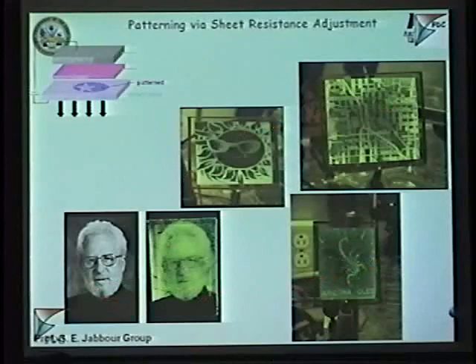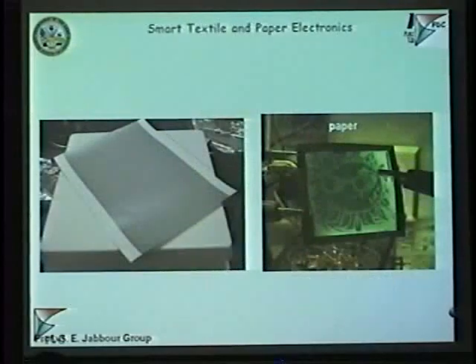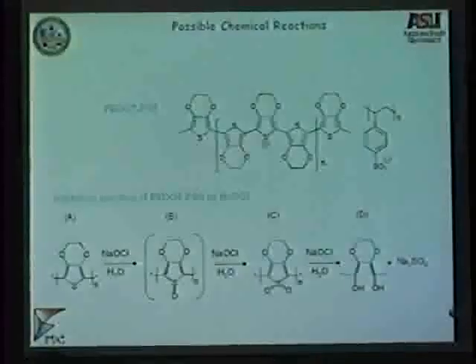It was scanned and printed, and then later we spin coated either the polymer single layer or 2 layers of small molecules. We did this also on paper, and these are the first application of large size OLEDs, or OLEDs for that matter, on paper. We did this way back in 2001 or so, and this is 4-inch by 4-inch substrates.